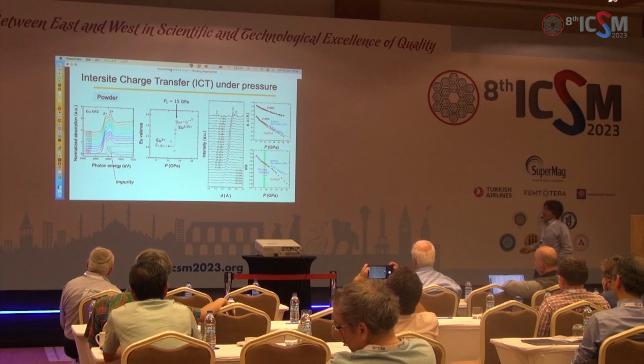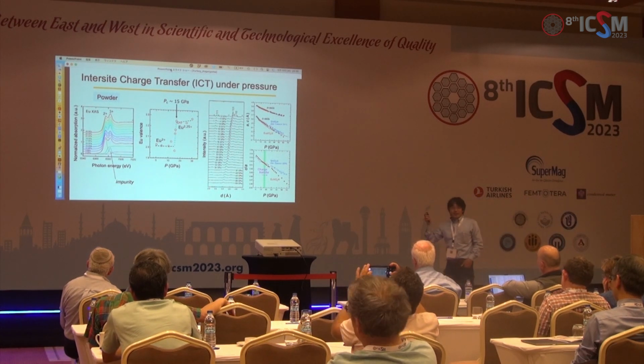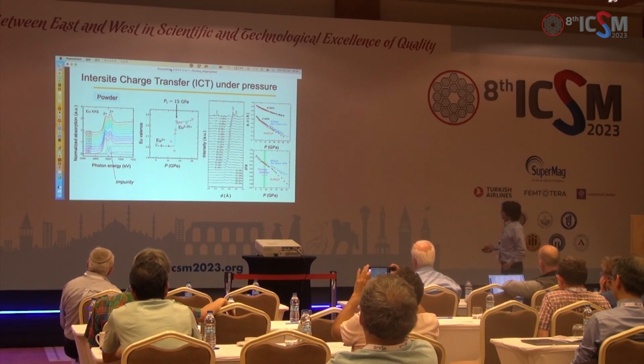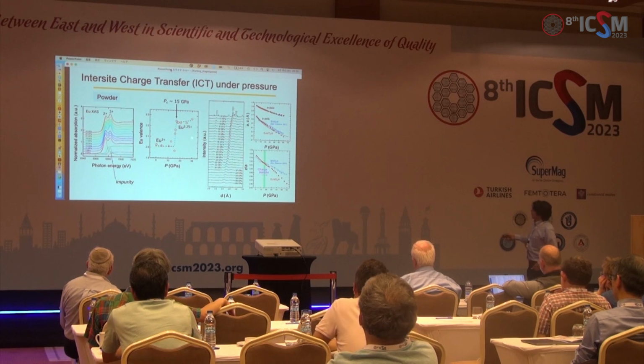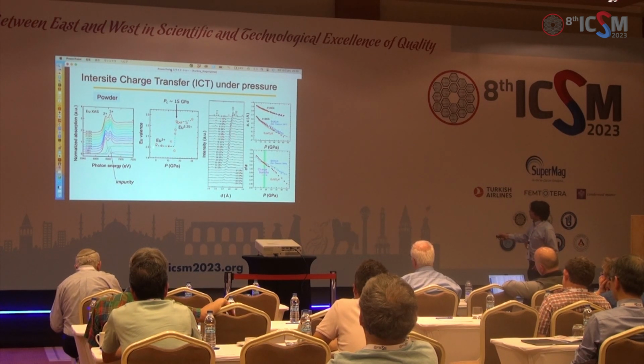Then we also applied high pressure. Then we did similar analysis, and we found that by applying pressure, we observed the charge transfer from the Eu2+ state to the Eu3+ state.